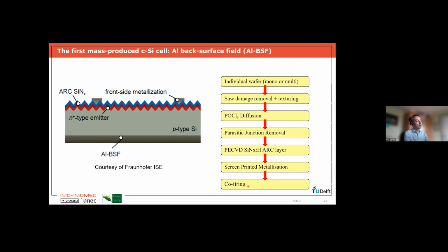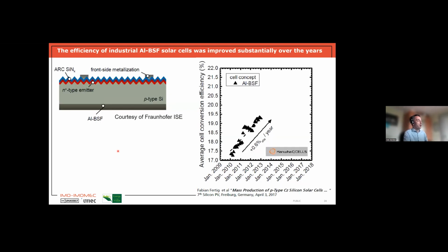So you put the whole thing into a furnace at high temperatures for a short time so that you form very good ohmic contacts on the front and the rear. And also during this high temperature firing step, you form this aluminium silicon alloy, the aluminium back surface field. So this is what was done, let's say, 10 years ago or longer. And so for many years, the industry used this process to make cells.